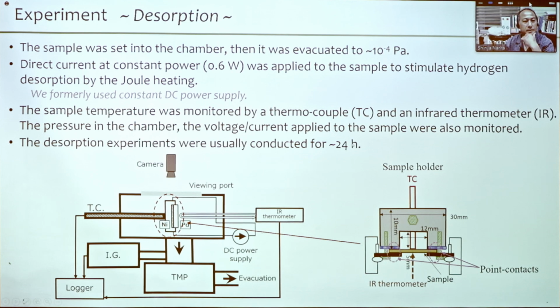Okay, so then the desorption. So this is the desorption setup. The sample was set into the chamber here. Then it was evacuated to about 10 to the minus 4 Pascal. And then the direct current at constant power of 0.6 watts was applied to the sample to stimulate the hydrogen desorption by the Joule heating. Well, actually, we formerly used the constant direct current power supply, but now we use the constant power supply instead. Yeah, this is one of the modifications of our experimental setup.